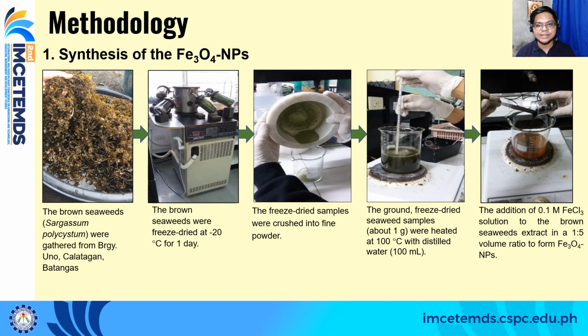The freeze dried samples were crushed into fine powder in order to do solvent extraction. The ground samples were heated at 100 degrees Celsius with distilled water, and then the synthesis proper of the iron oxide nanoparticles was done by adding the 0.1 molar ferric chloride solution to the brown seaweed extract in a 1 to 5 volume ratio, so that the iron oxide nanoparticles could be